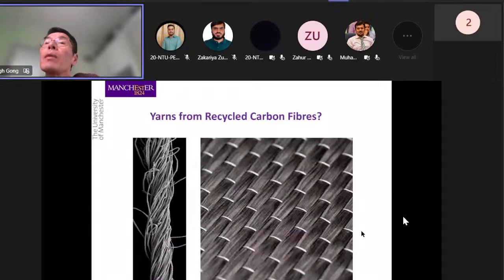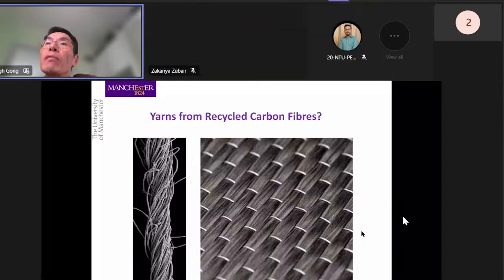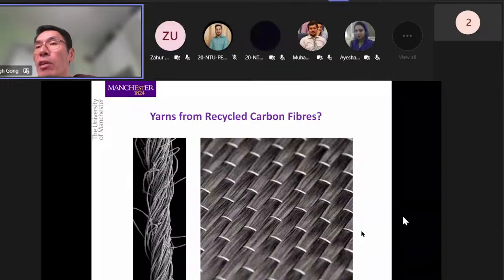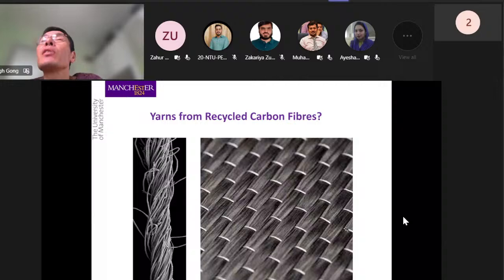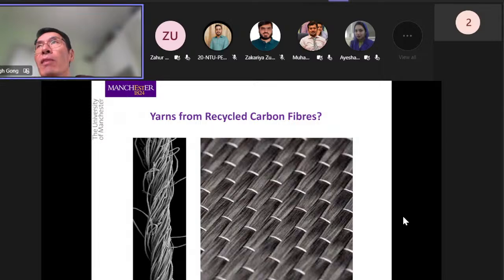Now, in the latest work we've tried to do, we tried to see whether we can produce yarns from recycled carbon fibers. Now, if we can do that, the advantage is quite significant, because we can then use the yarn to construct fabrics, or we can use the yarn to produce unidirectional composites as well. And that really brings the recycled carbon fiber in line with virgin filaments in terms of how we can use it. Although in terms of performance, absolute strength will still be less. As we know, staple fiber yarns will not have the same strength as filament yarns. So that's the same way.